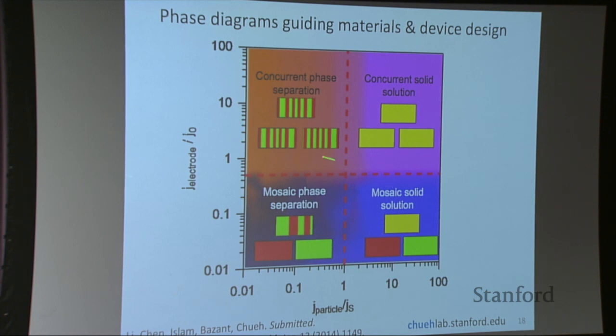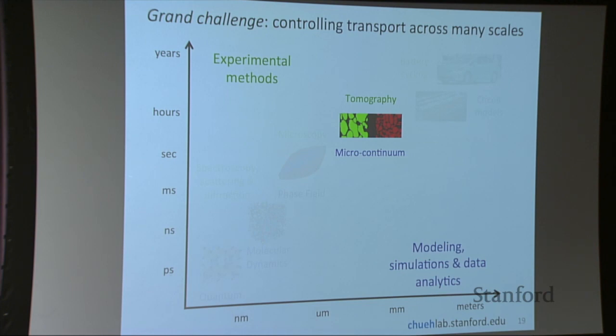But a lot of the time, the battery actually operates in this regime, which is the worst. This is when only very few particles are active, giving you the hotspots, and then each of those particles further undergoes phase separation. These stripes represent the movie I showed you where that high stress occurs at the interface. So this is good at the single particle level, but we're not done yet.